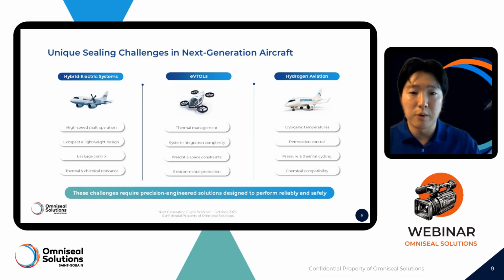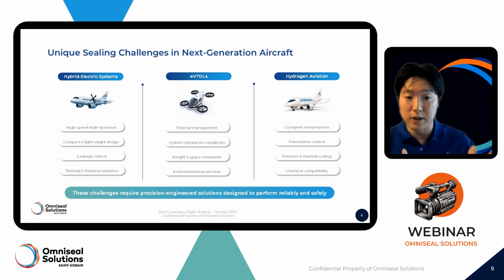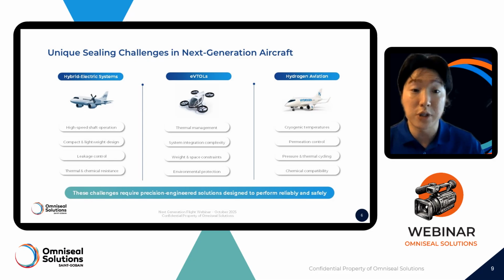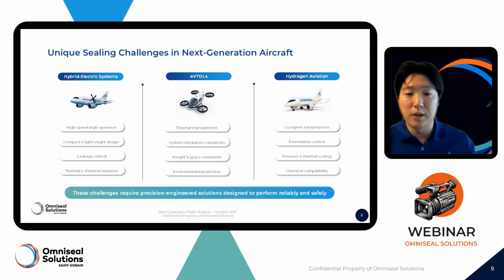While gaseous hydrogen is being considered for some, for really medium and long-haul travel, it'll be liquid hydrogen, right? So liquid hydrogen must be stored and transported at temperatures below negative 250 C or negative 418 Fahrenheit. And seal materials must stay flexible and effective in these cryogenic conditions. Permeation is another challenge here, as hydrogen molecules are extremely small and can permeate many materials, right? So not only the leakage, we also have to think about permeation through the seal materials. Seals must have very low permeability and precise geometries to prevent leakage.